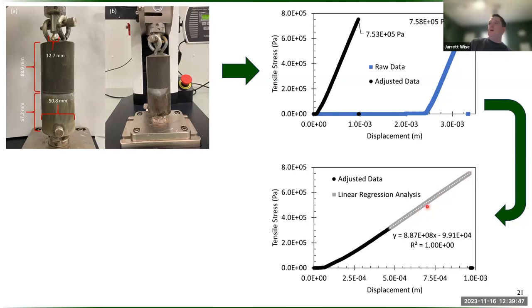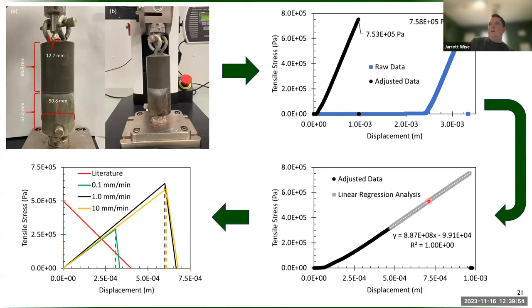So if we were to run this test and stop right here, everything goes back to normal and doesn't break, which is the opposite of what the literature says. The literature assumed that there's no separation, it just breaks and that's it, where we show there's actually an in-between spot where it doesn't break. The fascinating part is this is roughly 500 microns, so about half a millimeter. So you can get half a millimeter of separation before you actually cause that to fail.